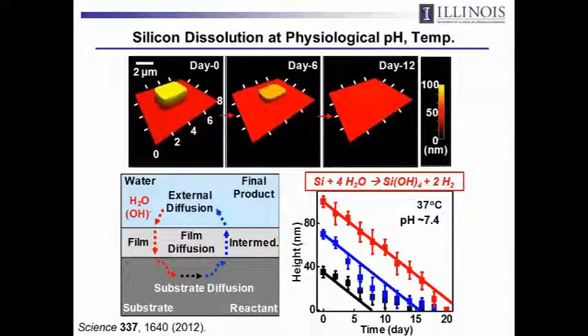And at these kinds of temperatures, it's almost completely gone in 3 weeks. The product of that dissolution is silicic acid, Si(OH)4. This is naturally occurring in your body. It's found in reasonably high concentrations in seawater, for example. So conceivably, at least at the dosages that we're talking about here, it's both biologically and environmentally benign.